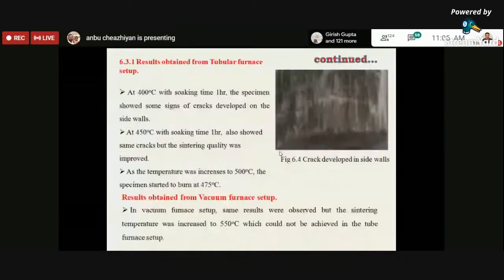Results obtained from the tubular furnace at 400 degrees centigrade with the soaking time, but the sintering quality was slightly improved when compared to that. If we try to increase the temperature to 500 degrees centigrade, the specimen tends to burn. That is the major drawback. We considered that it may happen due to the high temperature.